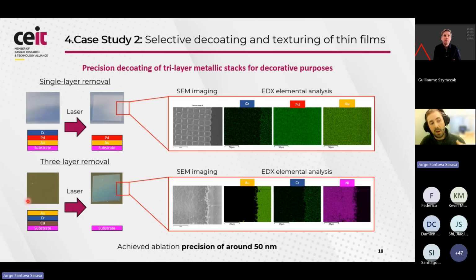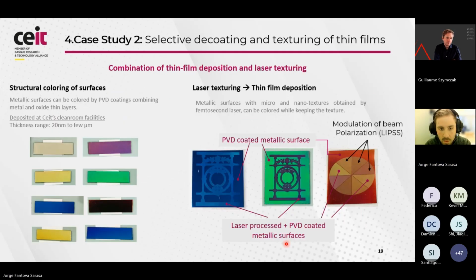In this case, we were able to remove the whole coating stack of 3 layers, starting from gold, and on the bottom was, let's say, a nickel substrate. And in this case, you see that the gold and the chromium have been eliminated, and therefore the nickel resurfaces or is revealed by the ablation, just giving off this bluish color. In this process, we achieved a precision of around 50 nanometers in this context.